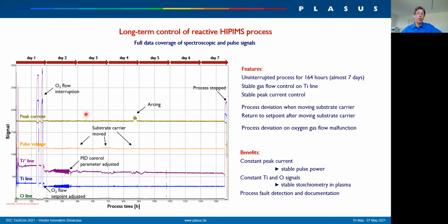And we made a control over a longer time. We want to show that a long-term control is really possible. We did this over 7 days. What you see here at the monitor tracks are the spectroscopic lines for oxygen, titanium, titanium plus, especially for high power impulse processes.